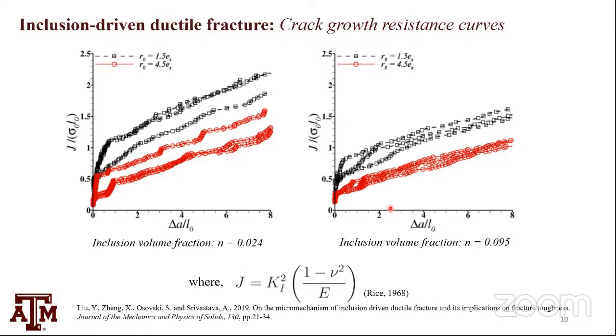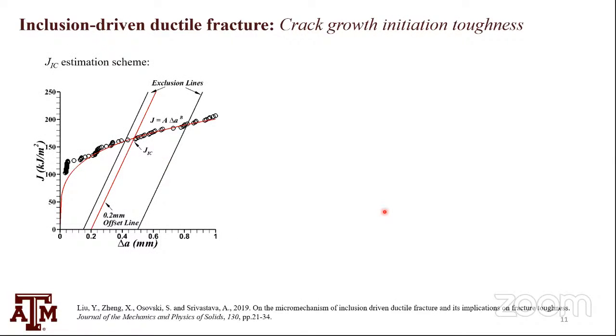So we can estimate the crack growth resistance curve like one would do in ASTM or in simple experiments. These are thin slices of material, but I forgot to mention that the front and back face of the specimen were under plane strain conditions. So it's a 3D microstructure, but still overall plane strain. That allows me to even define a J1C.